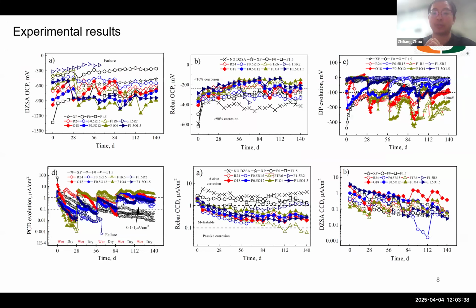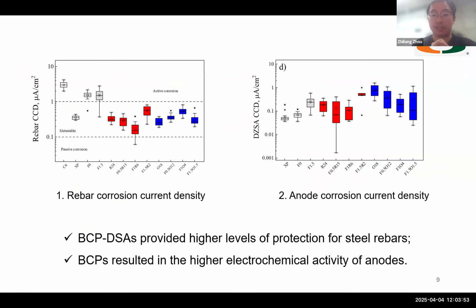This page gives you all the experimental results. I used 6 parameters to evaluate the effectiveness of sacrificial anodes, and let's get into the point directly. Figure 1 indicates the rebar corrosion condition. The reduced value can indicate the lowered rebar corrosion, that is, higher protection levels from the sacrificial anodes. We can see that those data with colors mean the sacrificial anodes with biochar addition. It has lower values, indicating these biochar-embedded sacrificial anodes can produce a higher protection level for rebars.